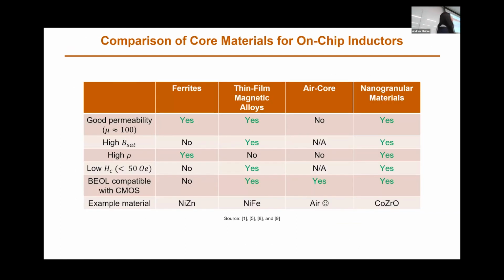And here is a comparison of basically what researchers have done for on-chip inductors in terms of core materials. So I mentioned ferrites because, again, power people have been using ferrites for decades. And there are ferrites that can operate at high frequency, like Alyssa said, like nickel zinc. But the main problem with ferrites is that they're not compatible with CMOS, because in order to make most ferrites, you have to anneal them at temperatures of like 1,000 degrees C, and that just doesn't work with CMOS.